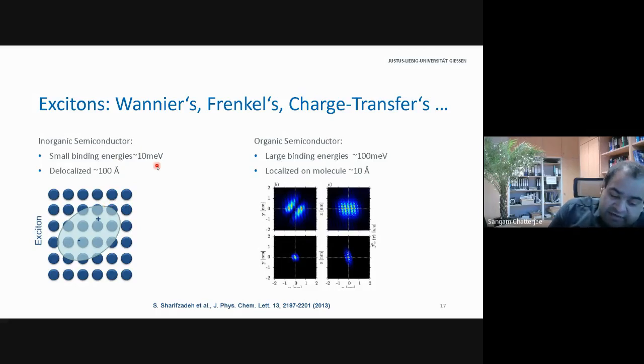Now, these binding energies are rather small in these systems. They're on the order of 10 millielectron volts. The reason is a large dielectric constant, typically, and the screening of the binding potential, which this results in. And these things are rather large compared to the crystalline lattice. So they're sort of delocalized specimens floating around in things like silicon or gallium arsenide. In molecular materials, the term exciton is commonly associated with the other extreme. That's a Frenkel exciton. And if you go into the literature, you will find that this is an entity which is totally localized on one molecule and one molecule only.